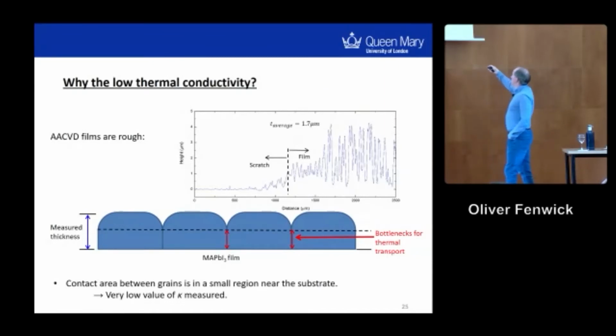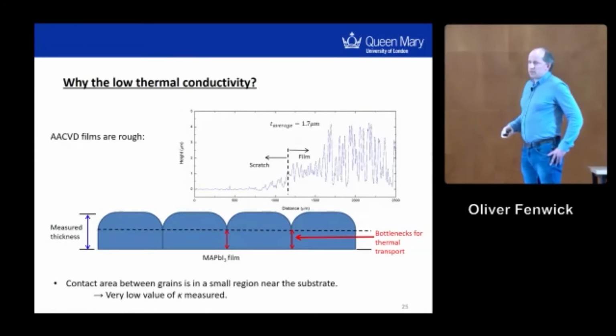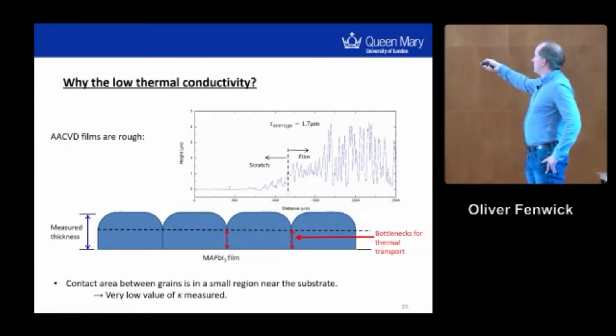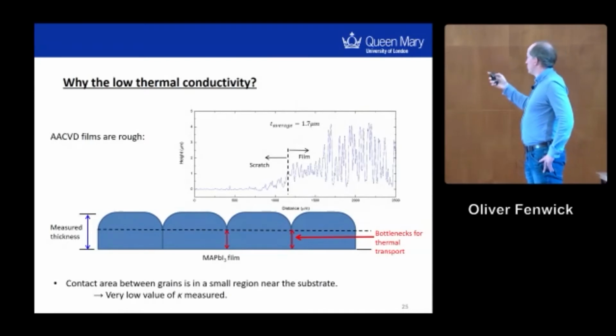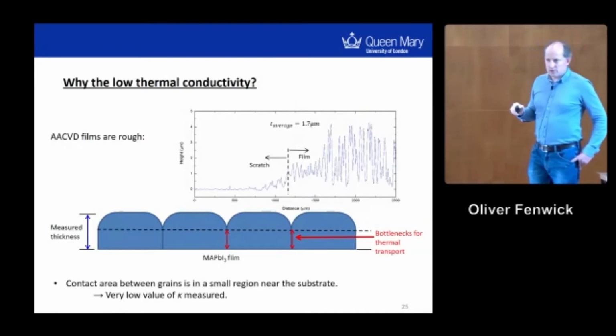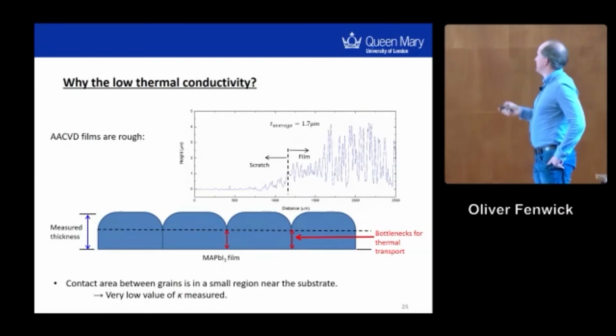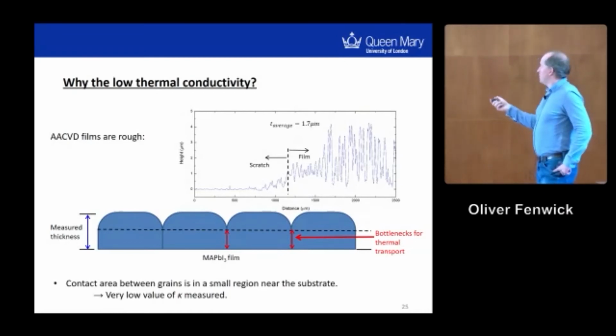They are 10% of the peak thickness at these points. These are bottlenecks for thermal transport. And that's something I want to talk about again at the end in a different scenario. But please be aware of this if you measure very low thermal conductivities. And this is not specific to this technique as well. I think this applies to all thin film in-plane thermal conductivity measurements.